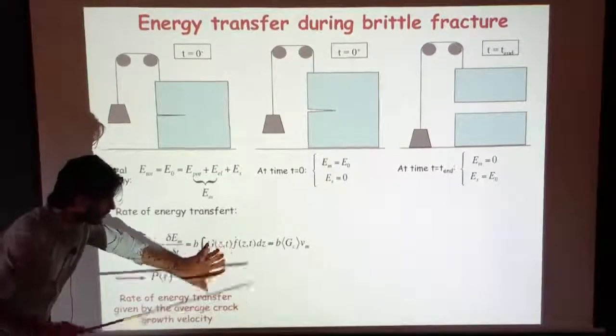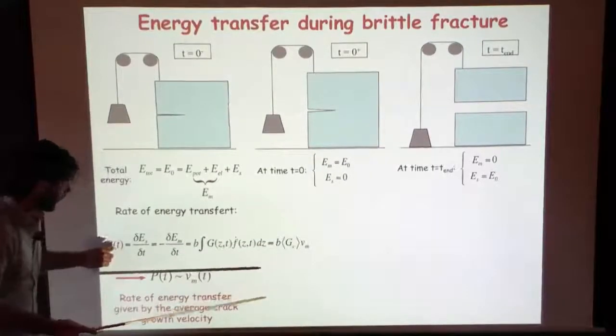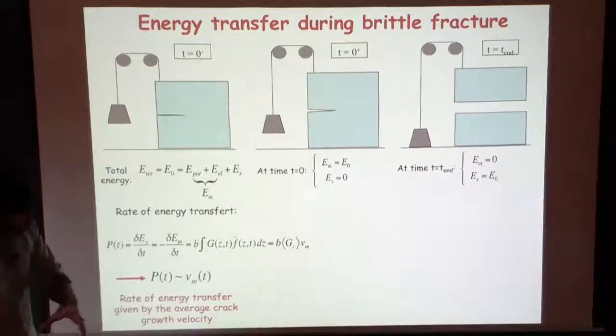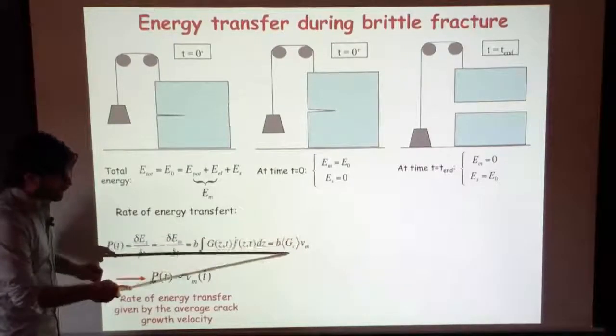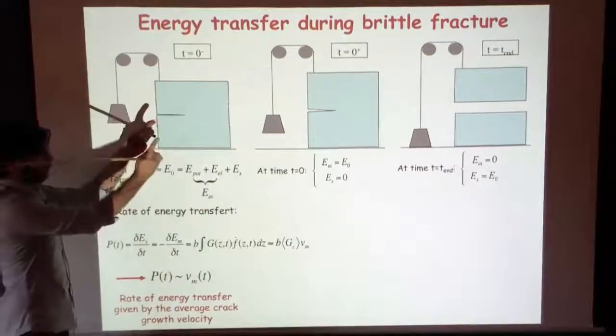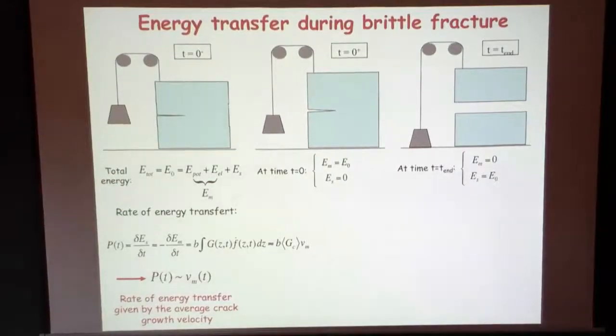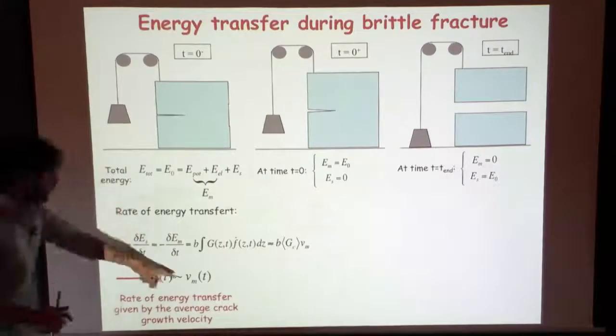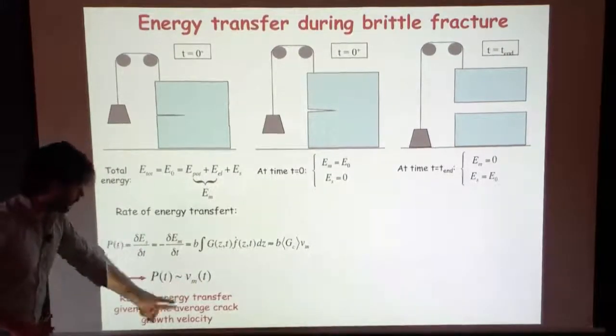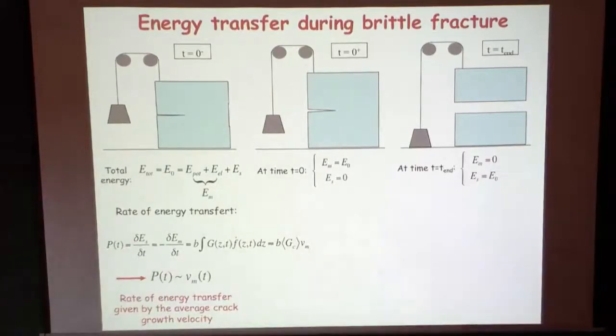And you can develop this term in two pieces and show that more or less the rate of energy transfer from mechanical to surface energy is proportional to the average crack growth. The constant is the average fracture energy times the specimen width. In other words, if you want to know the rate of transfer from mechanical to surface energy, you look at the velocity of your crack front, the average velocity of your crack front over Z. Vm is averaged along Z, not along time. This can vary with time. So this is a very practical way to look at the rate of transfer, and that will actually be the physical quantity in your problem.